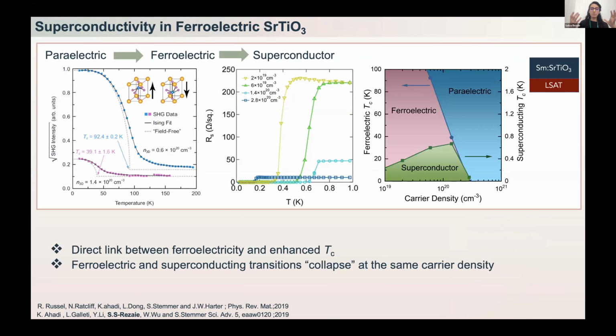But we wanted to make this structure superconduct, right? And for that, we start doping these structures. As soon as we dope these structures, the ones where we have low carrier density will still show this ferroelectric transition by an enhancement in the second harmonic generation signal. And if we cool them down even more, below 1 Kelvin, they will superconduct. If we put the two data points together, we can create this nice phase diagram for these structures. And as you can see, we still have this superconducting dome here.